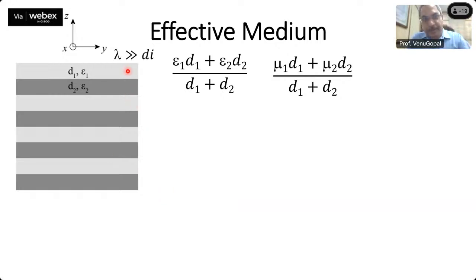However, we can have an effective medium whose dimension is of the order of the wavelength or bigger, but it is made of multiple constituents whose individual dimensions are much smaller than the wavelength of light. For example, we can have two materials of epsilon 1 and epsilon 2 dielectric constant. Mu, we can take as 1, so these are non-magnetic materials for simplicity, or we can consider mu 1 and mu 2 as well. Let's say thin films of thicknesses d1 and d2 are much smaller than the wavelength of light. Then the effective epsilon for this case is epsilon 1 d1 plus epsilon 2 d2 by d1 plus d2, and similarly mu effective can also be written.